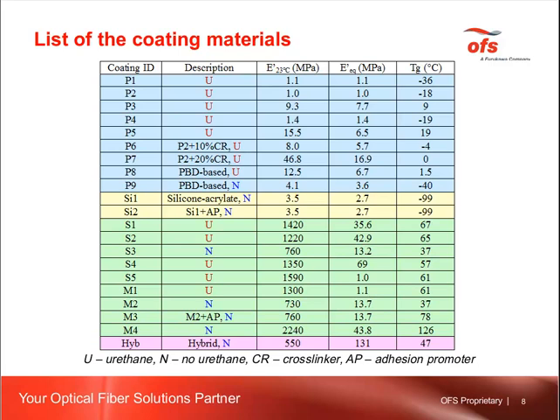Also, a hybrid formulation was utilized once. It was used as a monocoat. All these coating formulations have different chemistry. Some of them contain urethane, which is marked in the second column by U. Some of them do not have urethane, which is marked by N. In two cases, we added a cross-linker, CR, so primary coatings P6 and P7 were made out of P2 by adding 10 or 20% of a cross-linker.